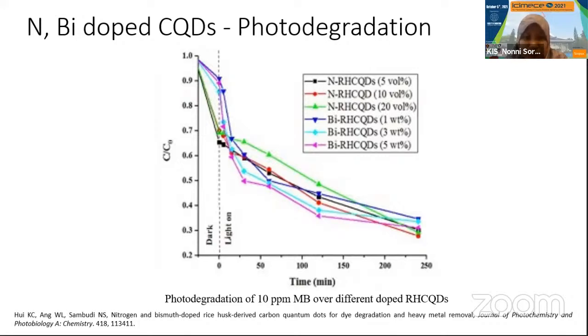It can reduce around 70% of the methylene blue after 4.5 hours. Okay, right? So when we dope, the performance is not better than the undoped particle of the carbon quantum dots. So from here, we can see that the sole use of the CQDs is very limited in doing its task.